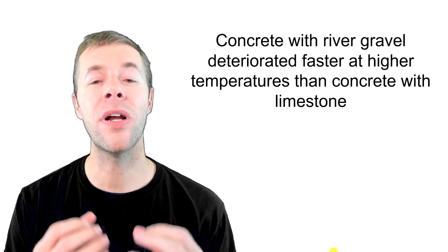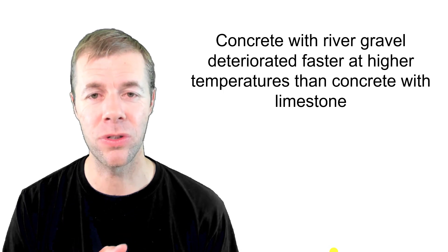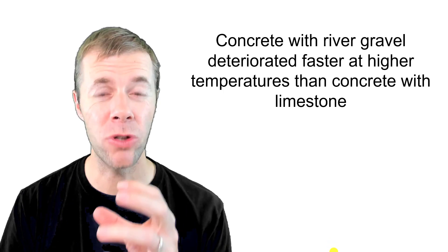So concrete with river gravel deteriorated faster at higher temperatures than concrete made with limestone aggregates. That's really important. It really depends on the aggregate you use inside your concrete.